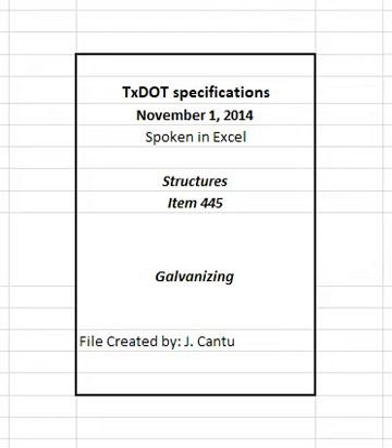3.5.2.1 Zinc-based solders. Remove moisture, oil, grease, dirt, corrosion products, and welding slag or flux from surfaces to be repaired. Clean surface to white metal by wire brushing, light grinding, or mild blasting extending into the surrounding undamaged galvanized coating. Preheat cleaned areas to at least 600 degrees Fahrenheit, but not more than 750 degrees Fahrenheit. Wire brush while heating and evenly distribute a layer of zinc solder. Flush the repaired area with water or wipe with a damp cloth to remove flux residue when repair is completed.